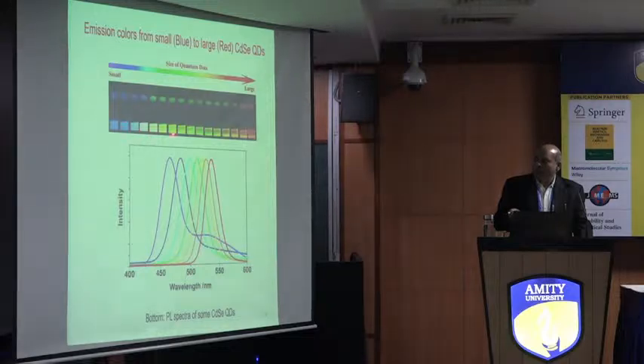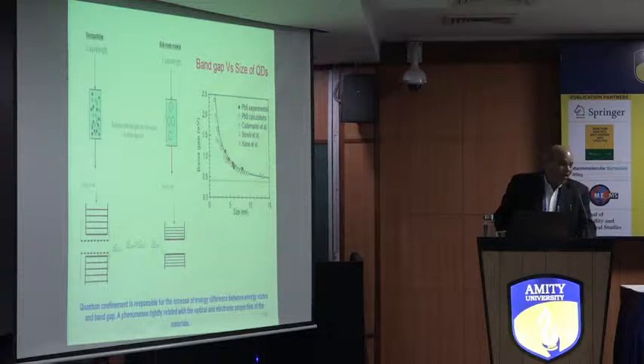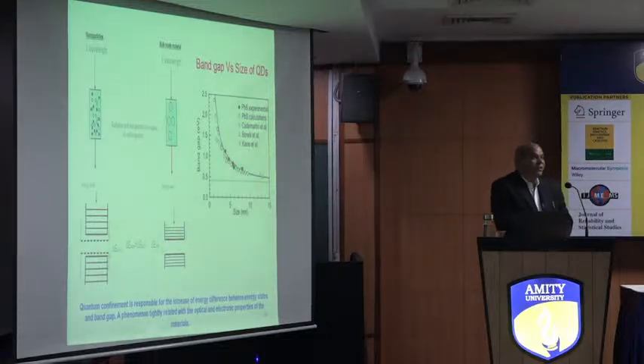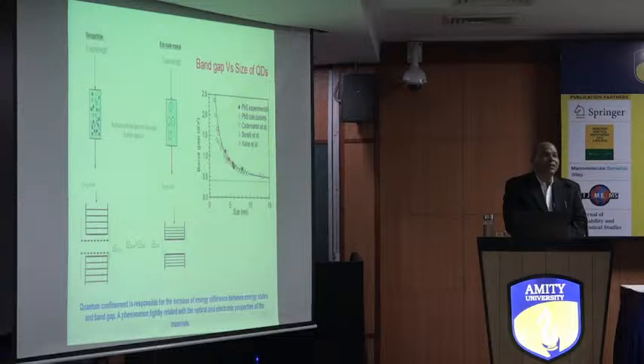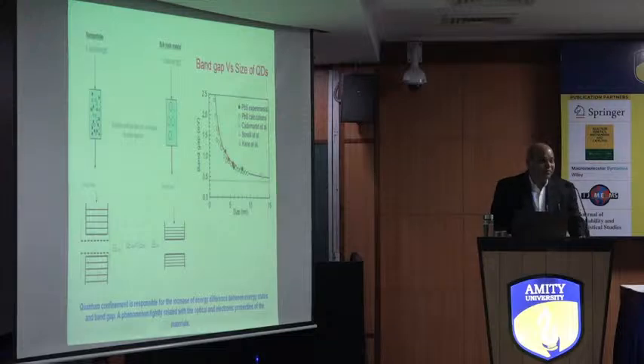If you put quantum dots under a UV lamp, the quantum dots will glow. And this is why we consider quantum dots below 10 nanometer. If you see the radius, most of these elements are below 10 nanometer. And second, if you see this graph, the band gap, for most materials up to 10 nanometer, the optical properties will change only in this region. So that's why we consider quantum dots below 10 nanometer.